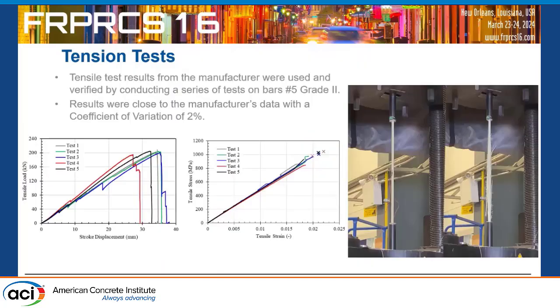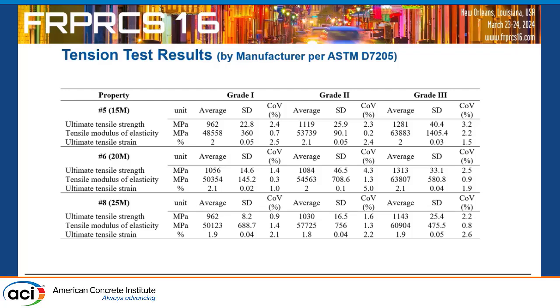We did not test all tension tests, which were provided by the manufacturer, but we tested one of the bars, one number 5 grade 2, in tension to ensure that we get the manufacturer-reported values, and it was consistent with that. So these are the values provided by the manufacturer, including the ultimate strength, modulus, strain, including standard deviation and coefficient of variation for 3 grades and the bars.